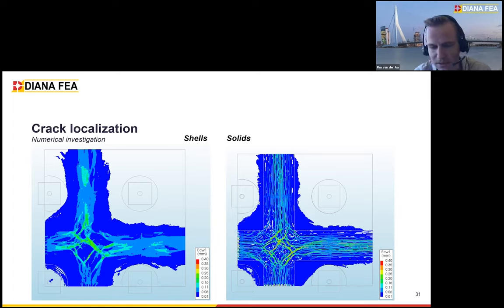Because indeed, if the cracks are smeared out over 8 to 10 elements, then it doesn't really work anymore to just use the crack bandwidth. You want the cracks to nicely occur in one element. Then what we discussed earlier, that for finite element analysis we're using the crack bandwidth as the characteristic length, is then also valid.